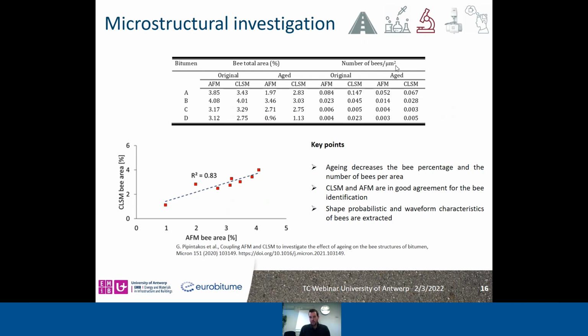The key points of this study support that there is a clear decrease of the bee percentage and the number of bees per area. And this is of importance since these bees have an association with the waxes in bitumen, which most of the times create deposition problems in the different stages of processing. We can understand more about their crystallization with aging afterwards or with oxidation during the different stages, from production until paving of bitumen. Also, the two microscopy techniques, CLSM and AFM, are in good agreement, as you can see in the bottom left, with regard to the bee identification as witnessed by the bee area percentage.